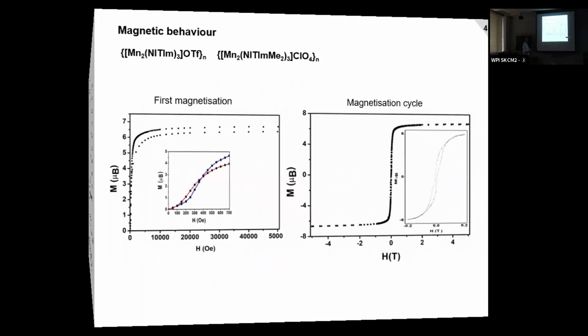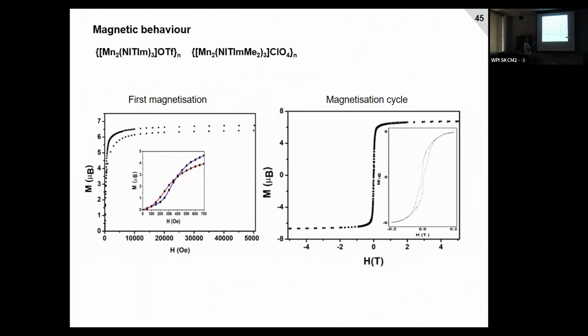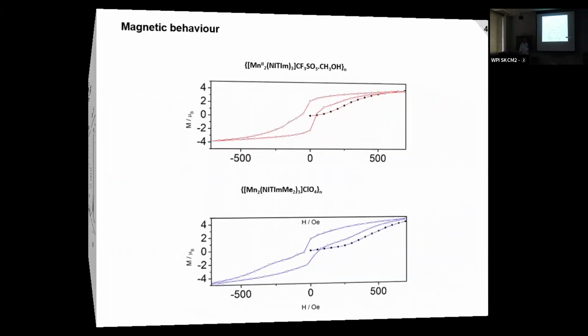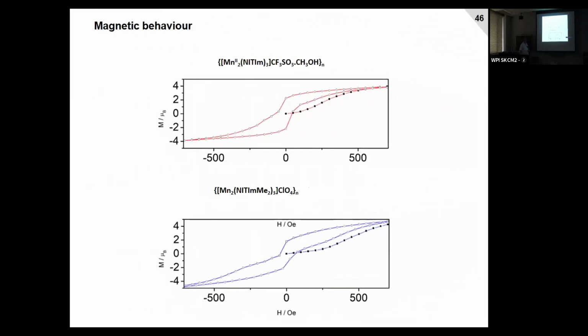If we look at the magnetization, still we don't have a complete saturation, we don't reach 7, but smaller. And here you can see that we have a hysteresis loop, but the hysteresis loop closes at a value which is not the expected saturated value. So this is reminiscent of weak ferromagnetism and spin canting.